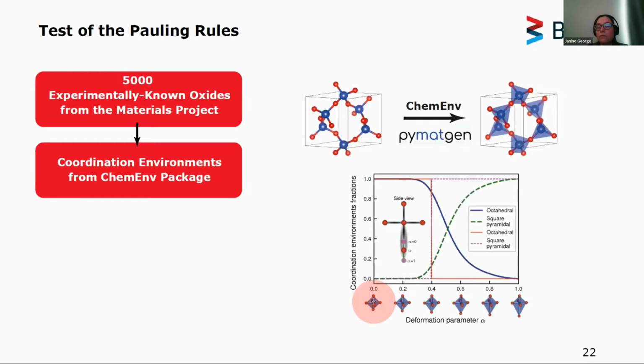One of the advantages of this algorithm is that if you go, for example, from an octahedron to a square pyramidal coordination environment, you do not get a sharp transition as you would have in many algorithms. So at some point, you would just have 100% octahedron, and then you deform it a little bit more, you would go to the square pyramidal coordination environment. It has a smooth transition between these coordination environments.